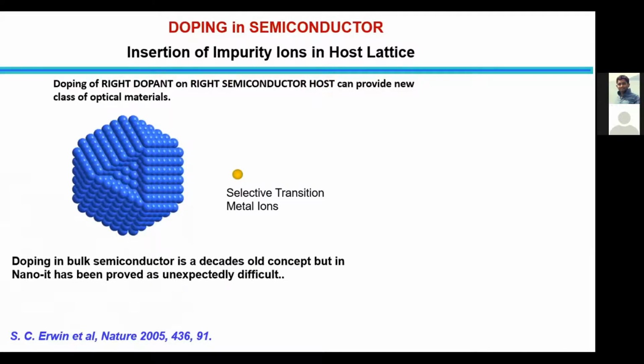It's not like interstitial doping. It's not like you have an extra atom inside the crystal. It's not like doping in silicon. It's like you are replacing one cadmium atom inside the crystal. Suppose this is a foreign ion, like manganese or copper, which are mostly used, and if you dope it, it just replaces one of the atoms of the host nanocrystal. That means, let's say it's cadmium selenide, and it removes one of the cadmium ions from there,